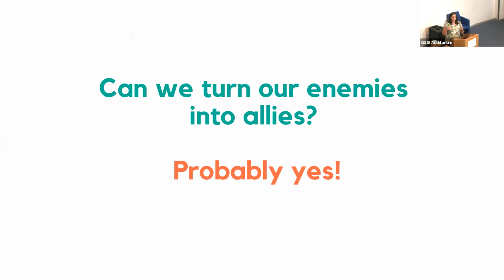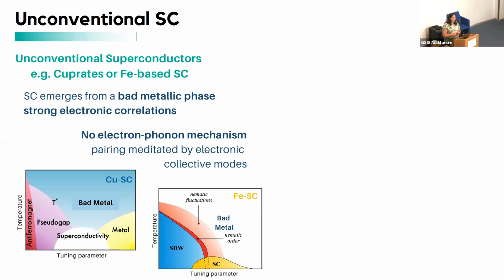Can we turn these enemies into our allies somehow? This is actually where I want to go. I want to talk about unconventional superconductivity. In unconventional superconductors, I want to mention just two families, cuprates and iron-based superconductors. Superconductivity emerges by lowering the temperature in both cases from a very bad metallic phase, characterized by strong electron correlation. The mechanism is not electron-phonon, and pairing is probably mediated by electronic collective modes.